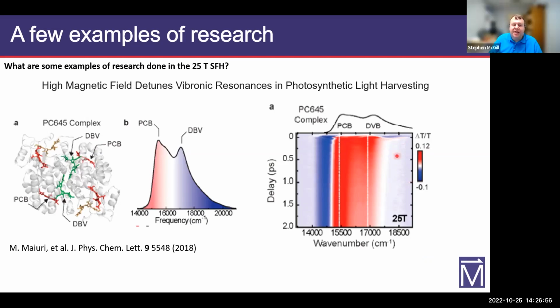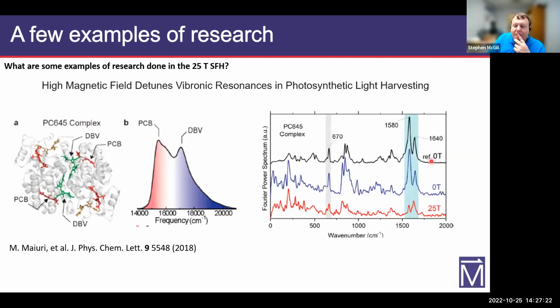Well, so there's an intermediate state that it has that's a singlet state, and the field moves the energy of that intermediate singlet state. Actually, there's two excitonic states once it's excited, and those two overlap with each other. What you can see here, this is the only example of this that I can show you in this presentation. But essentially, if you take that time resolved data, there are some oscillations.